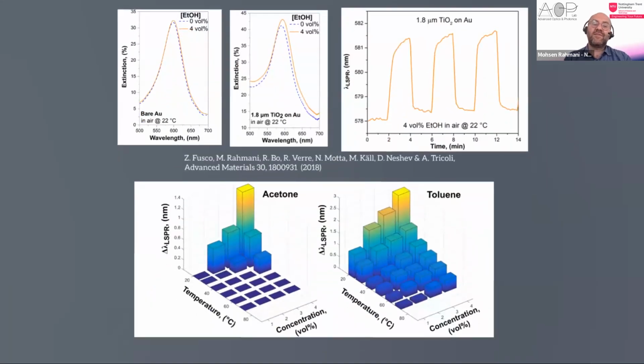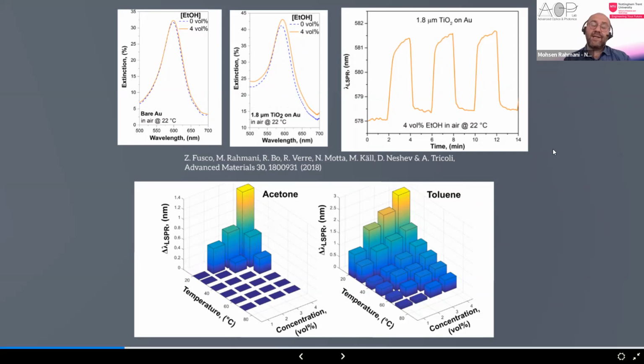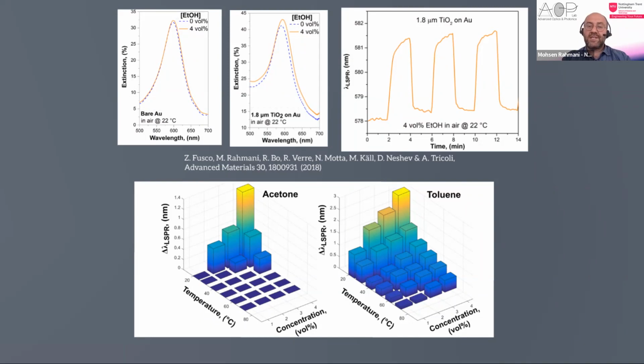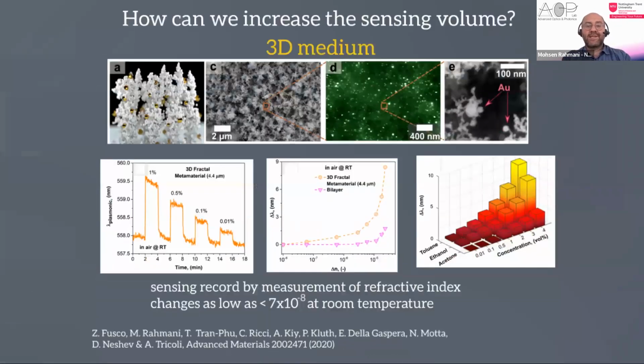So we used it for detecting different kinds of gases in air: acetone, toluene, ethanol, and as you see, they have different signatures, which was very interesting. If you take temperature into account, and have this data set of different gases, you will be able to use the same sensor not only to detect certain gases like acetone, toluene, and ethanol and say what the gas is, but you can even detect the concentration of those gases. So it is very exciting and very interesting results, which was very well received in the optical sensing community, and that's why we were very excited to continue in this research direction.